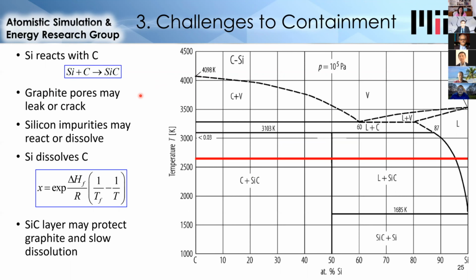This can also cause the graphite to crack as it's bulk converted to silicon carbide, which results in a volume expansion. Another problem is that the impurities in silicon could react with the graphite or cause the graphite to dissolve more. And the next biggest problem is that silicon dissolves carbon. So this is true of all liquids contained in solids, just to varying extents. This equation shows that the solubility, which is X, a number between 0 and 1, is related to